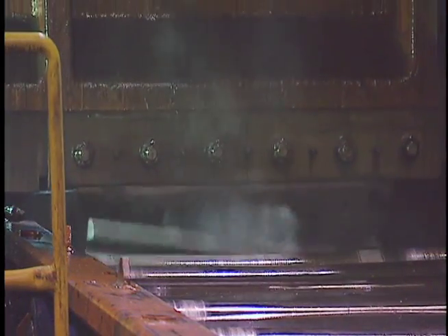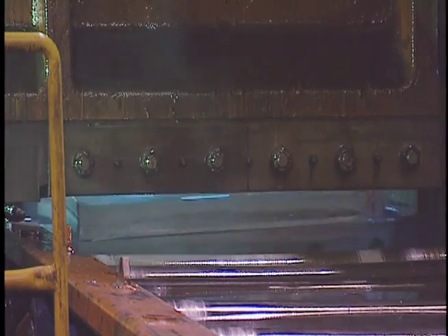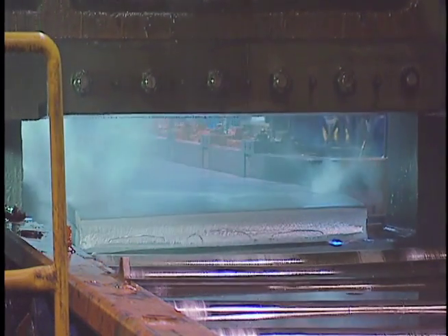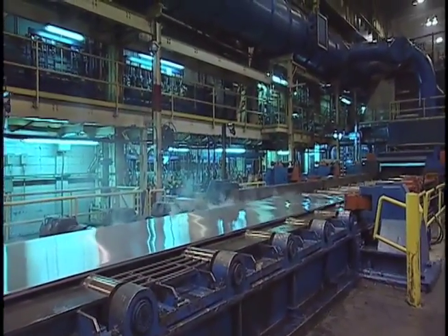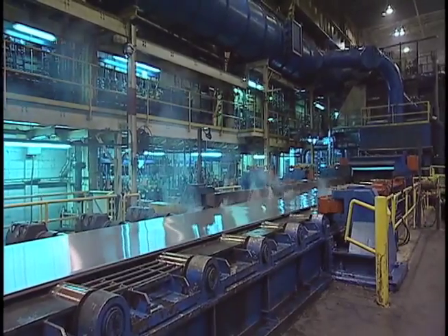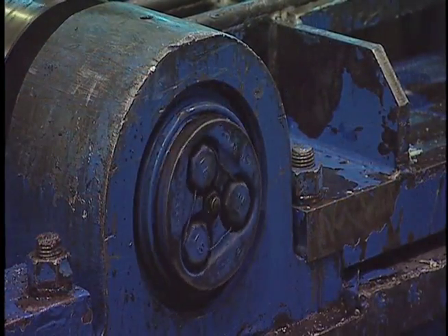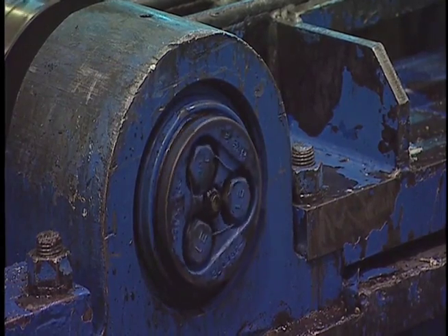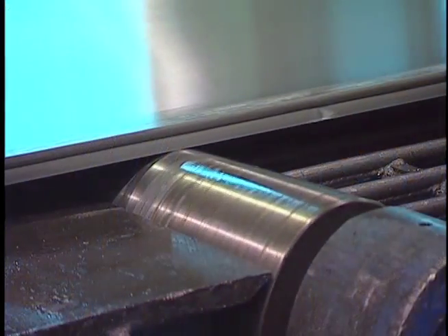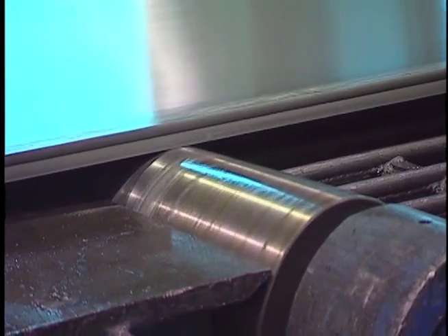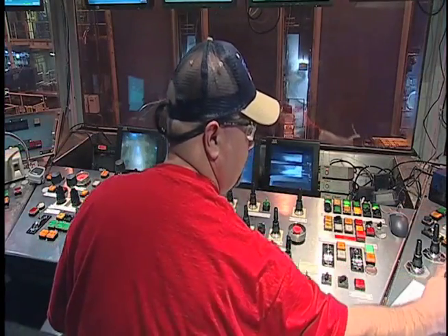Once the ingot has reached a thickness of 6 inches, it will pass through the 6-inch shear, where a portion is removed. After 6 more passes, the slab will be 1 to 1 1/10 inch thick and is transferred down the rolling table, which is over 200 yards or 2 football fields long, to the 2-inch shear and the finishing mill. The 2-inch shear will remove another portion of the slab and it's fed into the finishing mill.